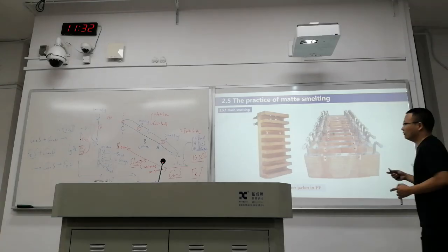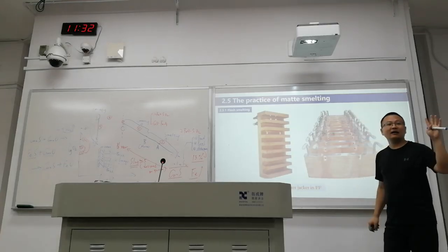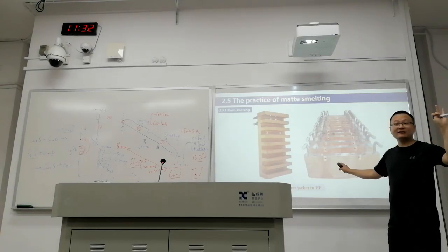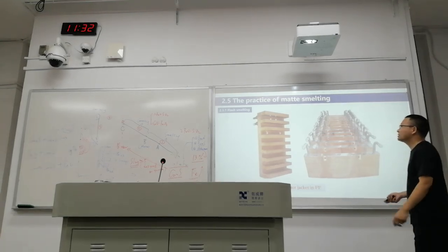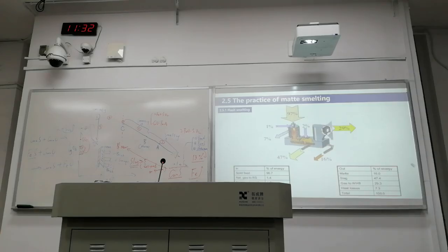Okay, so we know this is a very important component: the burner, the steam dryer, and the water jacket. Three important components in flash smelting furnaces. And if we are going back to the energy balance, we know that the input energy will mainly come from the solid feed, which can be interpreted that when we are running the matte smelting process, the energy is supplied by chemical reactions. And the chemical energy is stored in the copper concentrate. And sometimes when we are initiating or improving the conditions, we are adding some natural gas or some oils.